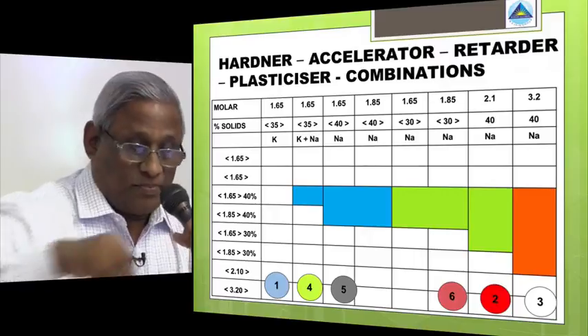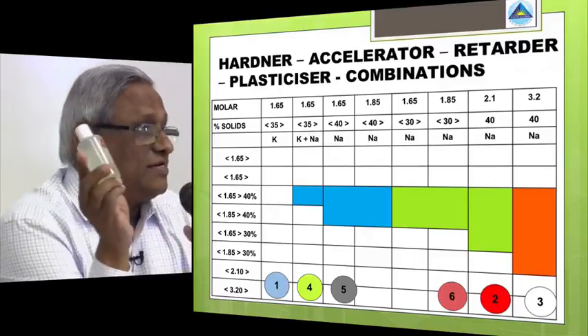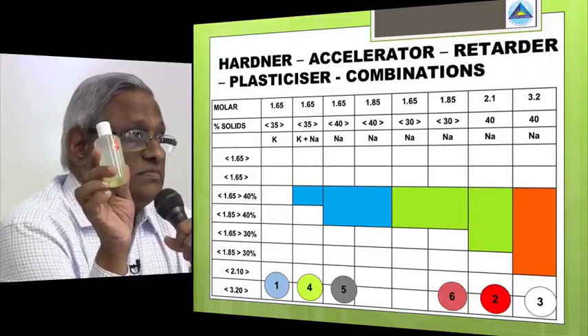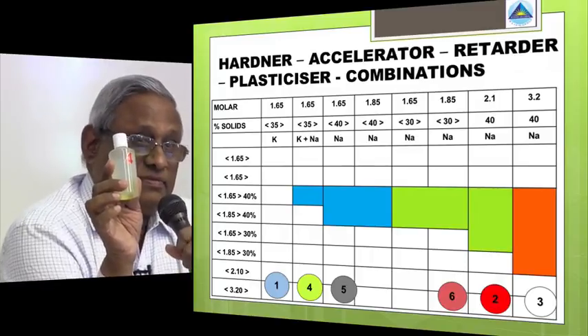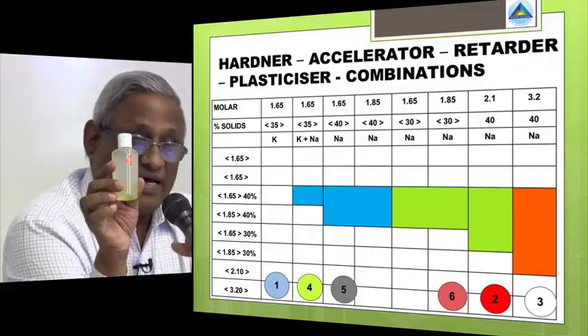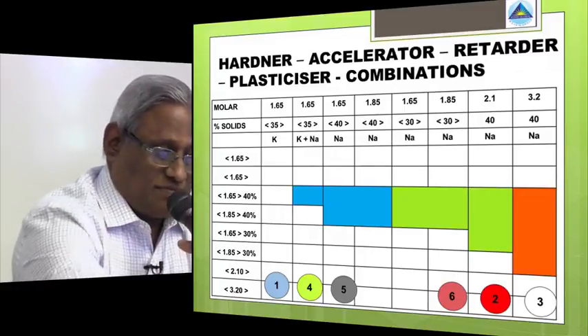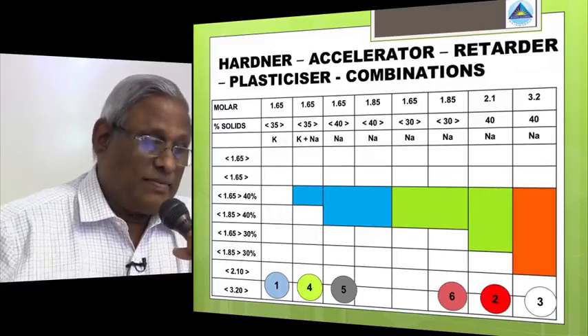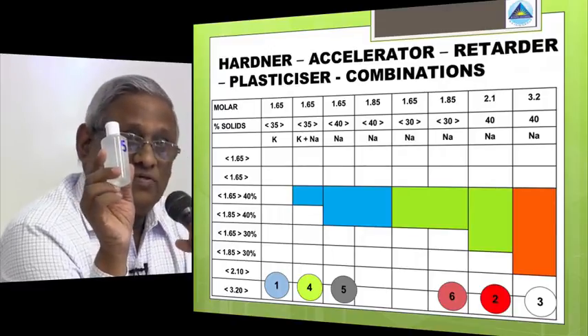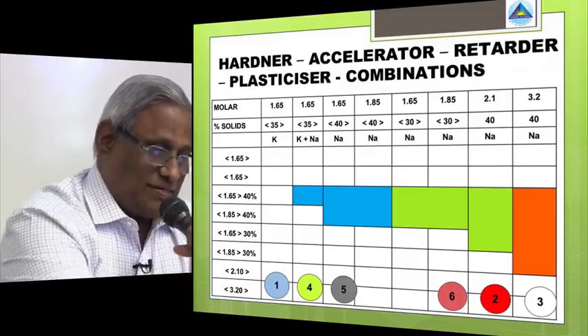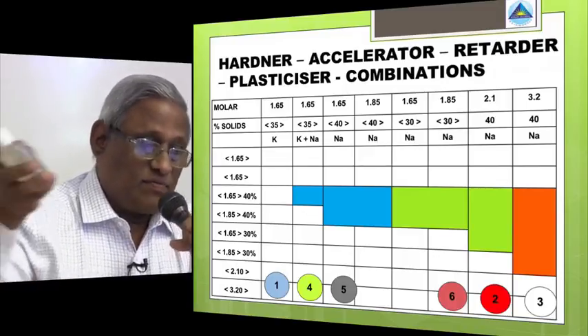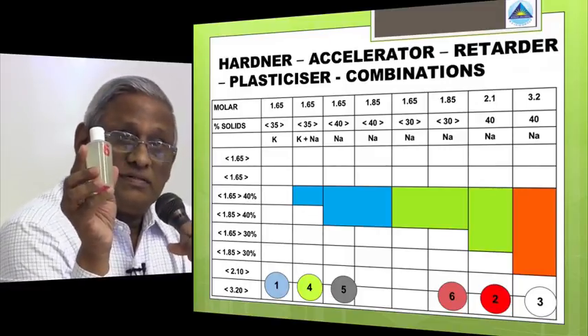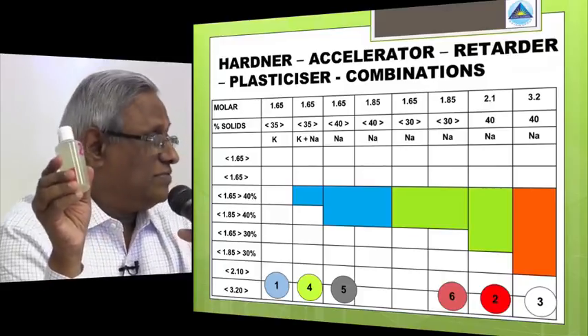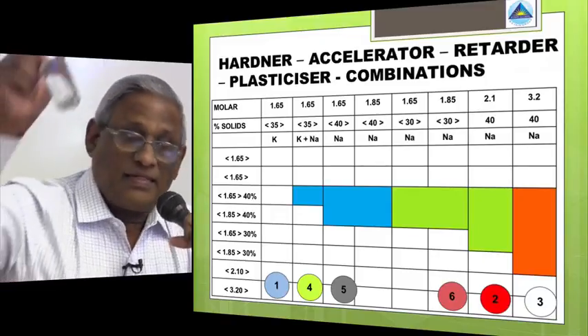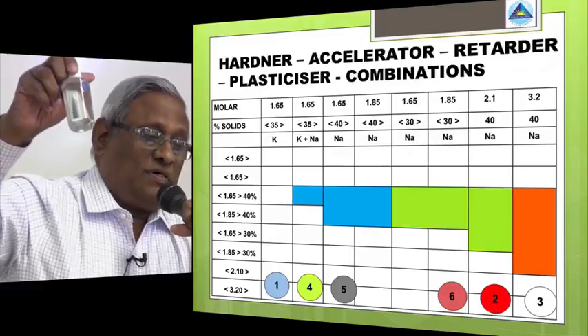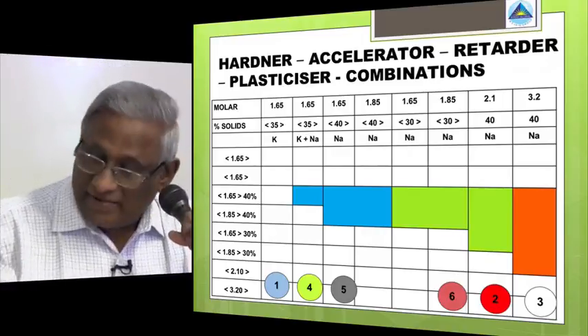And we have this, actually this is a potassium. And this is a combination of potassium and sodium, in the ratio of 1/3, 2/3. And this is also the ratio of 1.65 molar ratio, with solids of 35%. And this is sodium, 40% solid content, 1.65 molar ratio. I will tell you what the colors indicate there. And then I have this, a 1.85 molar ratio with 30% solids, and this is a 2.1 molar ratio with 40% solids, and this one is a 3.2 molar ratio and 40% solids.